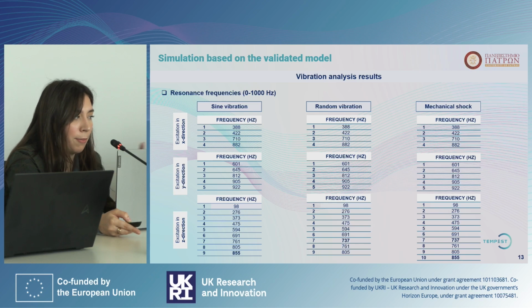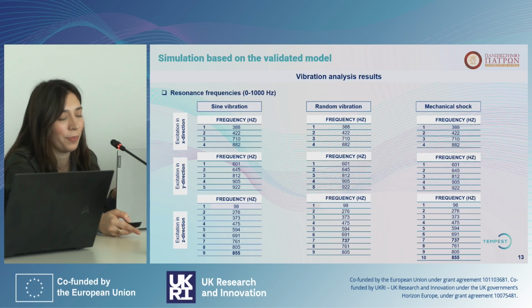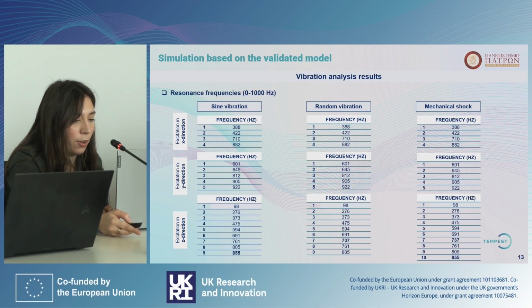However, it can look alarming at first glance because we applied three different loads and we got the same results. This can be due to the boundary conditions that we used, which were the same for all three loading scenarios, and the fact that the power spectral density curves, which show the signal power over the frequency spectrum, have the same amplitude, which means that the signal is distributed in a similar way for the three loading scenarios.